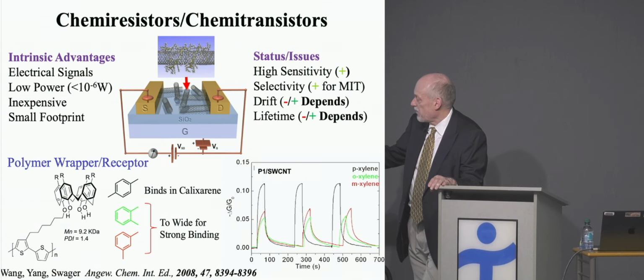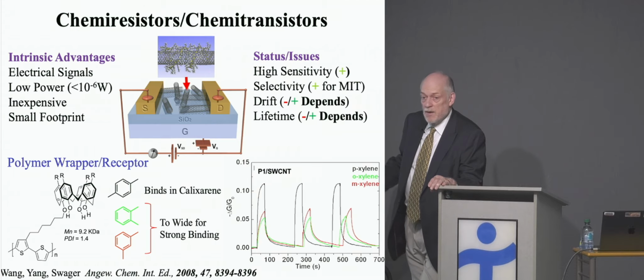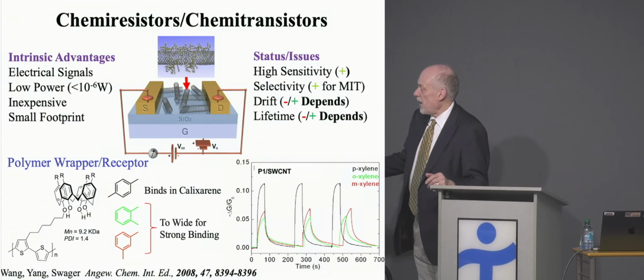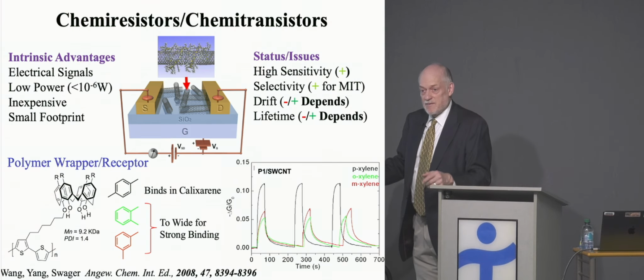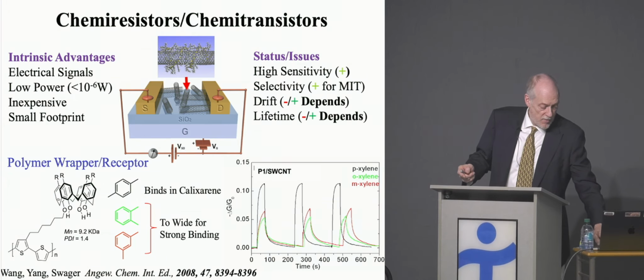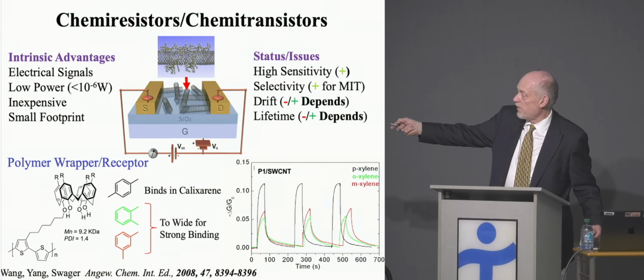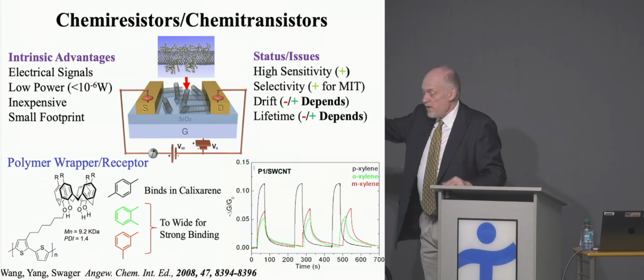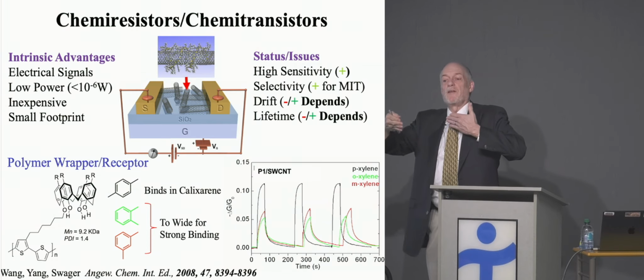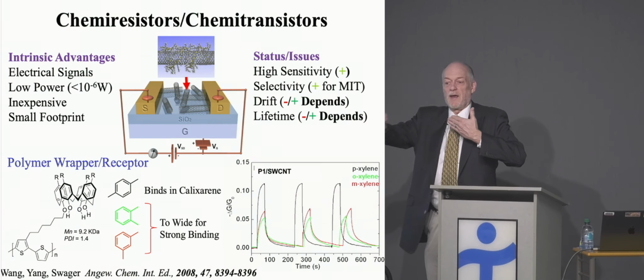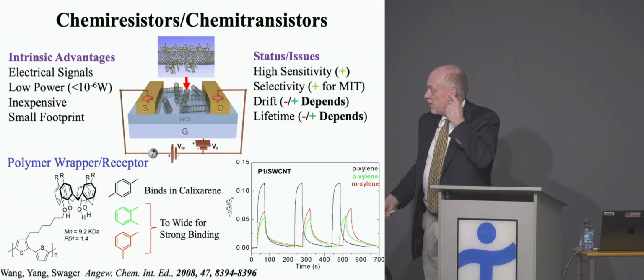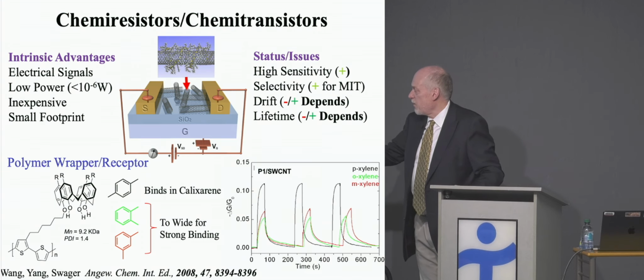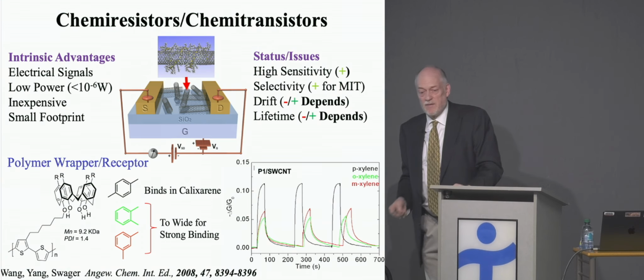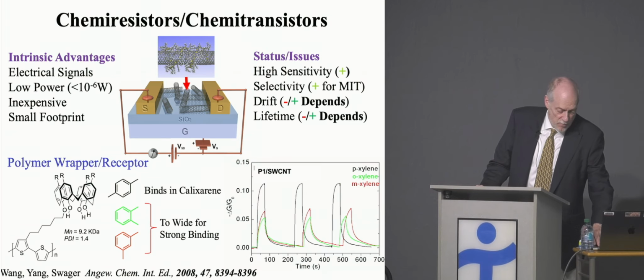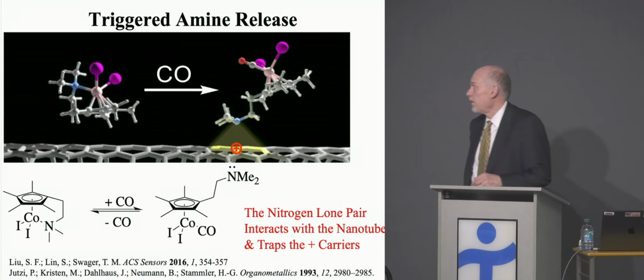You give it a little blast, it backs down. And so this is negative. So the current is lowering. It's becoming more resistive because what's happening here is this bucket is collecting these things, and then over here between the nanotubes, this little corona is getting fatter, and it pulls the nanotubes apart, and the electrons can't get between the nanotubes as easily. So this is that swelling mechanism, and we found that we could get differences between these that we expected based on what we understood about the chemistry.